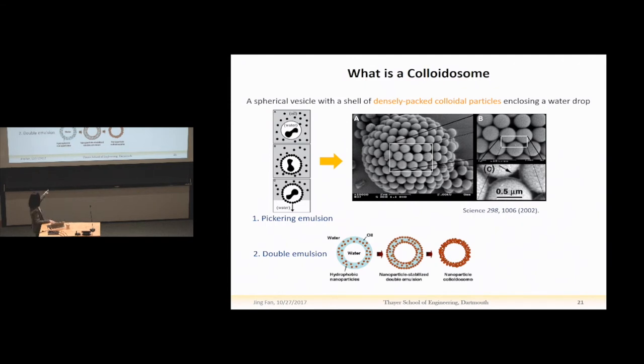In this case, we have a water-in-oil-in-water double emulsion, and we suspend nanoparticles in the middle oil phase. And after removing the oil from the double emulsion, we have the nanoparticles left to enclose the water drop for a colloidosome. So obviously, a colloidosome can have either one layer of particles forming the shell or multiple layers. And colloidosomes, similarly to liposomes and polymersomes, were proposed as a potential drug carrier for targeted delivery.